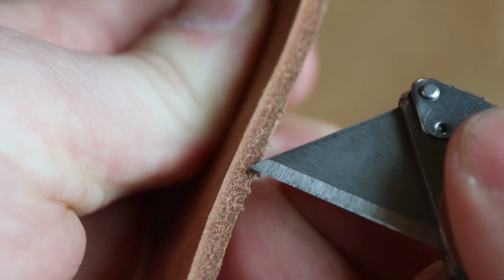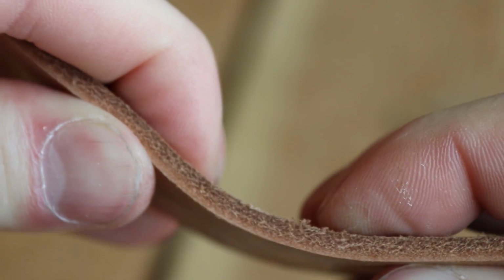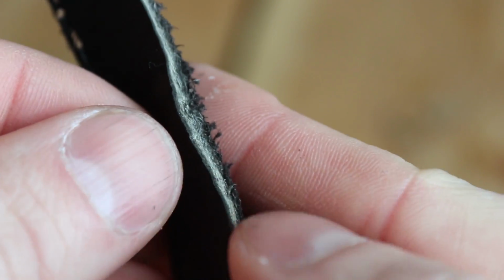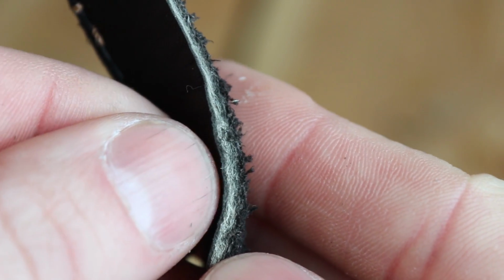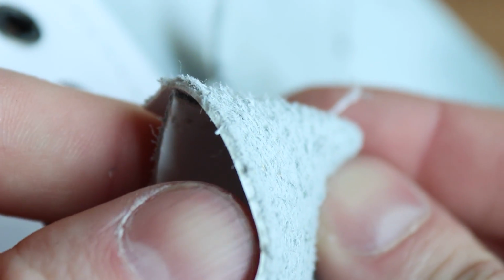Versus a higher quality leather, it's tanned slower and more thoroughly, and a lot of fats and liquids and oils are worked into the leather, which create a really heavy, dense, more solid feel to it. So that's not always the case, because sometimes you can take a really high quality leather and tumble it to soften it, and it gives it a foamy feel. But if it's really dry and it's foamy and the top layer feels like it's slopping around a little bit, that's usually an indicator of a poor leather, especially if you see some bluing on the inside, like we talked about in the previous videos, because if it was dyed really fast and they didn't re-tan it, you're gonna see some of that bluing from the chrome tanning salts in there.